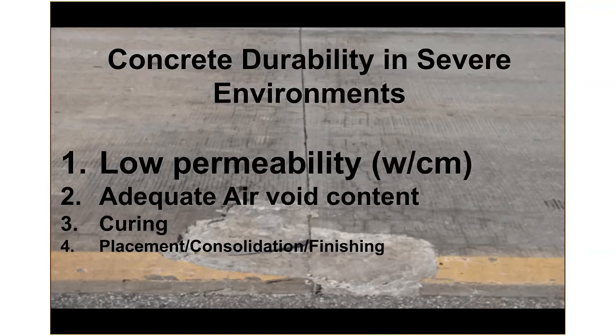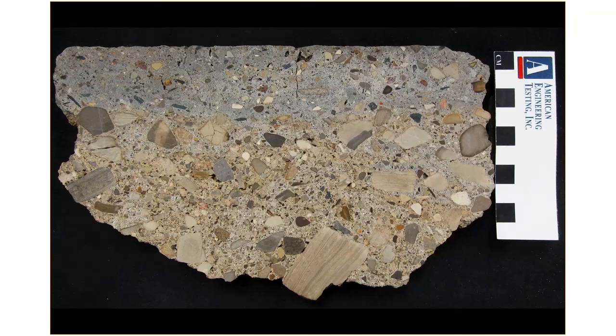Now this is a saw cut and lapped cross section of this pavement, and this pavement was about 8 inches thick, 6 to 8 inches thick, and we can see the top of the pavement is at the top, the bottom of the pavement is at the bottom, and we've got this lapped cross section.